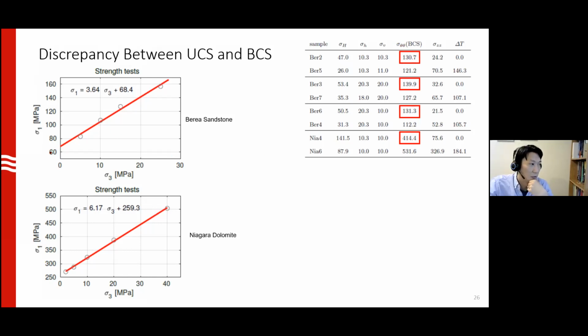On the left is the rock strength constrained by conventional triaxial tests on a cylindrical sample. You can see that the UCS is about 70, or maybe around 250. So you can see that the rocks are failing at, well, not at least a factor of 2, but significantly higher strength, because UCS here is 70, but then it's failing at 130. For the dolomite, it's around 250, but it's failing at 400 megapascal. This is actually approaching the maximum stress we can apply. So this is a big problem for us.